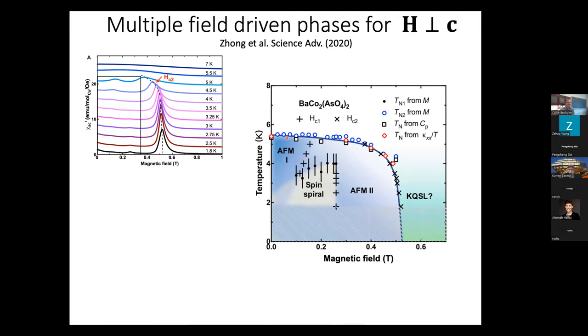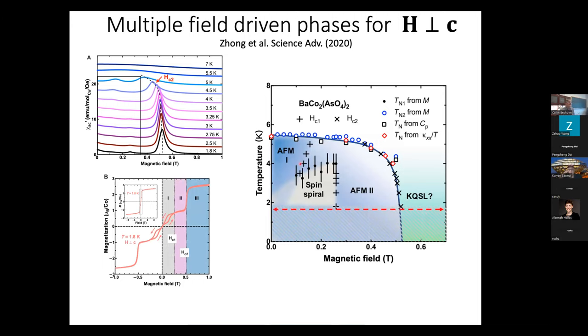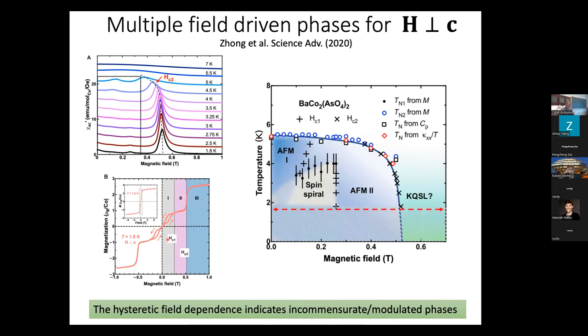So here we have then the field temperature phase diagram. Temperature is the vertical axis. And here's this field-driven phase transition at low temperatures. And here is, from this 2020 paper by Zong and Kava, the question mark Kitaev quantum spin liquid phase, which was considered to possibly be present, a little bit like in alpha ruthenium chloride, in this field range where you end up suppressing the magnetic order state. But as indicated here, there are additional phases existing as you apply magnetic field at finite temperatures. You can also see, if you look at magnetization versus field and trace an entire hysteresis curve, that there's quite complicated stuff going on at really low fields, and in fact those are very much signatures of some kind of incommensurate magnetic order that's developing in the compound.